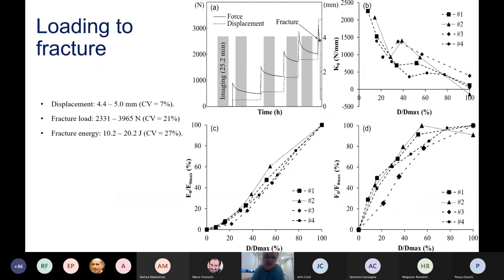So let's have a look at what we've got. Displacement between 4 and 5 millimeters, fracture load in a range below 4,000 newtons, and fracture energy between 10 and 20 joules. Top left, you see the force and displacement time history and the time frames where we did image, and as we normalize the forces and the energy by the maximal displacement, by the maximum value that we calculated, we see here displayed the normalized energy, normalized force, and the stiffness.